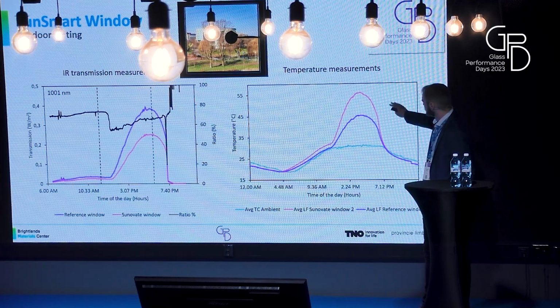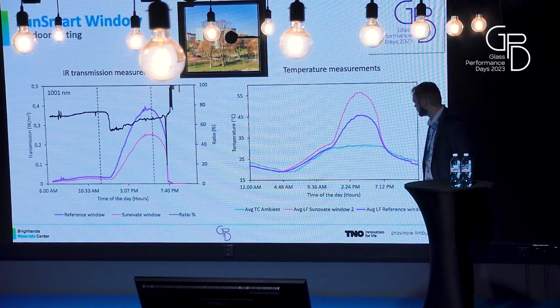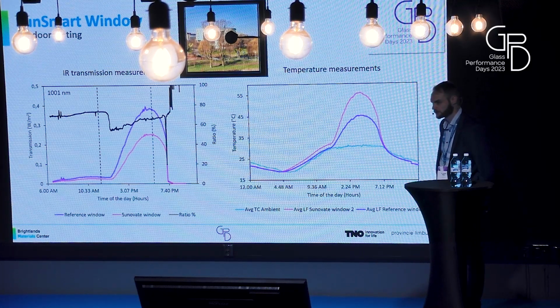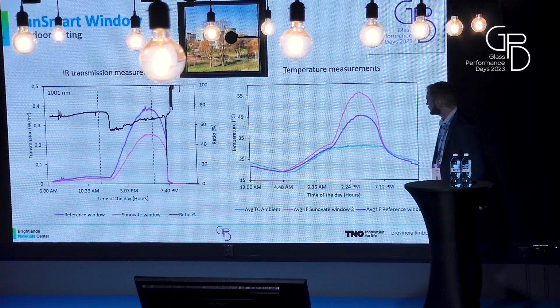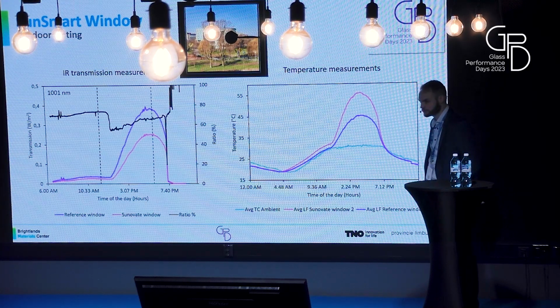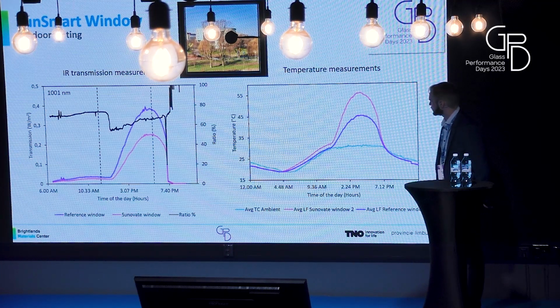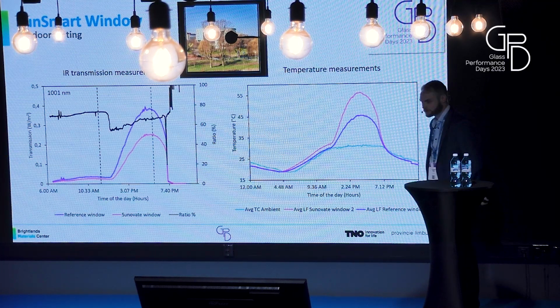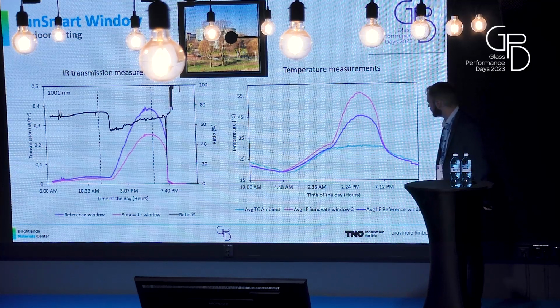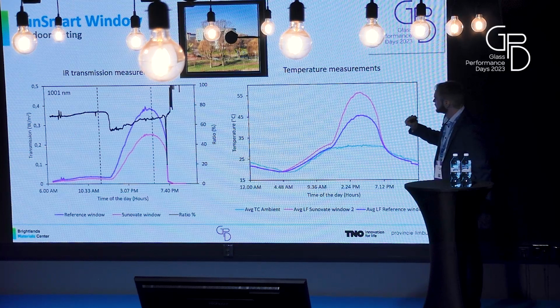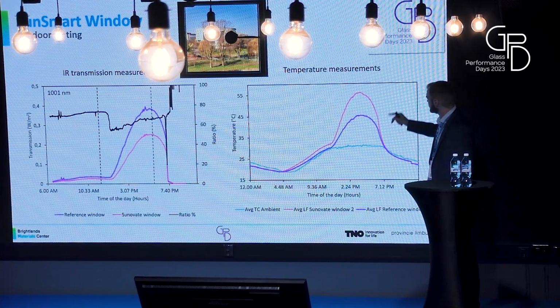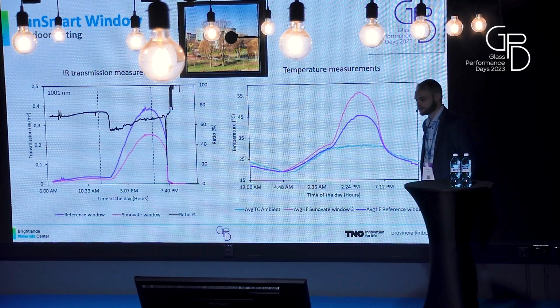As I said, we are also monitoring temperature. What's quite interesting here is that when you compare the ambient temperature to the glass temperature, already the temperature of the reference glass is about 15 degrees higher at the maximum temperature than the ambient. But we also see that the temperature of our thermochromic glass exceeds that again by something like 10 degrees. So the temperature, since the switch is based on temperature, we also need to consider that the glass temperature will be much higher than the ambient.